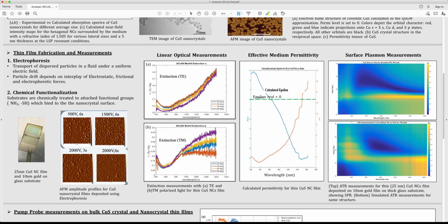Interestingly, the extracted optical permittivity of the effective medium of these thin films predictably had a plasmonic character to it, and we subsequently demonstrate the presence of surface plasmons on these nanocrystal films.